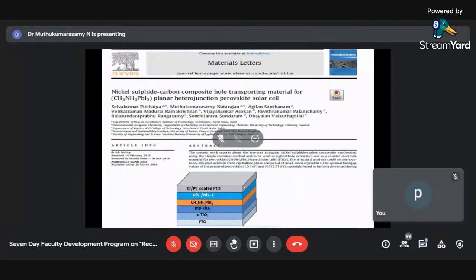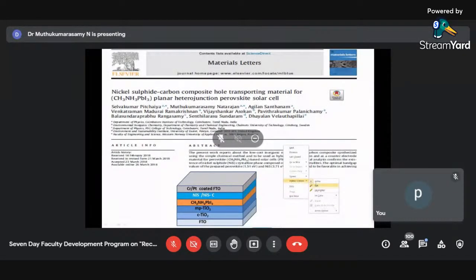So we started to work with perovskite material, particularly with methylammonium lead iodide from the year 2012 onwards, to be more specific. And we fabricated methylammonium lead iodide based perovskite solar cells, and we went with a planar type of structure. You can see the structure which I have given below is the structure which we fabricated in our laboratory. We had FTO, then compact TiO2, then mesoporous TiO2, then methylammonium lead iodide. Then we didn't go for any organic type of hole transporting material. We used nickel sulfide and carbon incorporated nickel sulfide as the hole transporting material, and we got an efficiency.